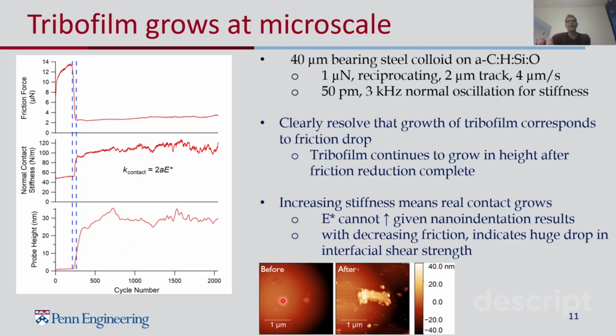And then finally, we have imaging before and after, where we reverse imaged the ball surface. What you can see is that before the experiment, the ball is very, very smooth, and we only see the hemispherical shape. After the experiment, we see, in fact, that the tribofilm is formed here. And the thickness of this tribofilm matches approximately the change in probe height we measured throughout the experiment. So I think this shows pretty conclusively that we form a tribofilm and that the tribofilm is responsible for a huge drop in the friction.